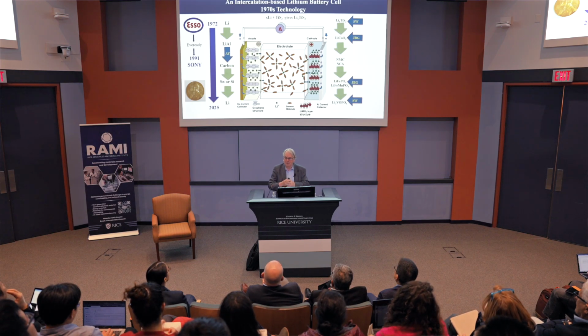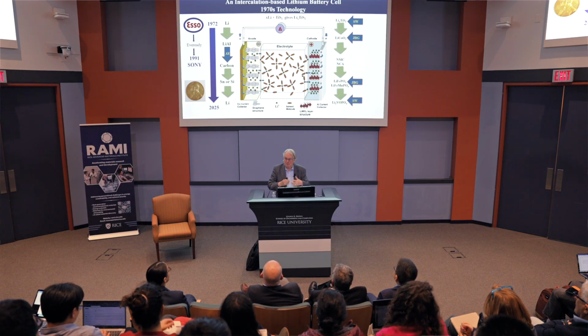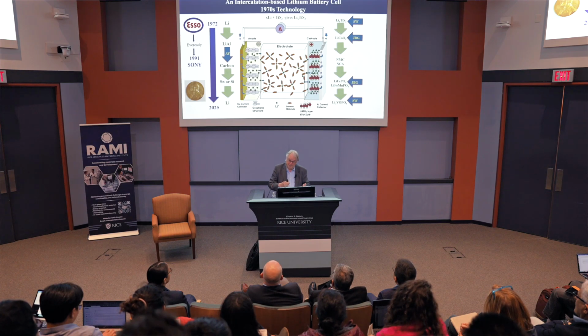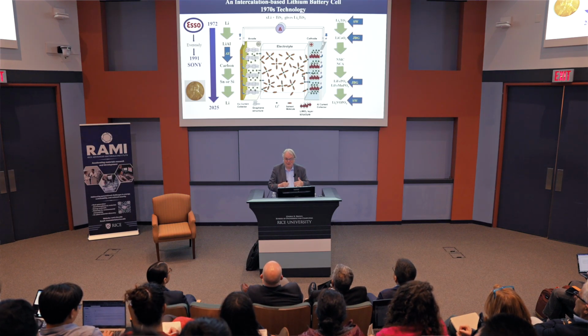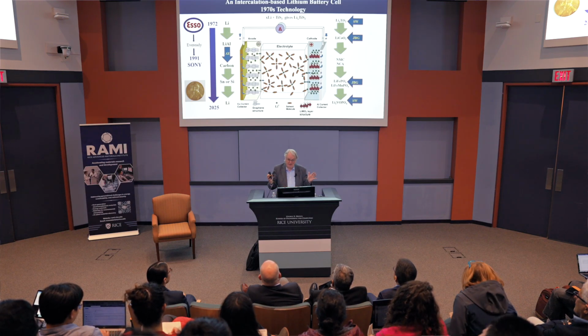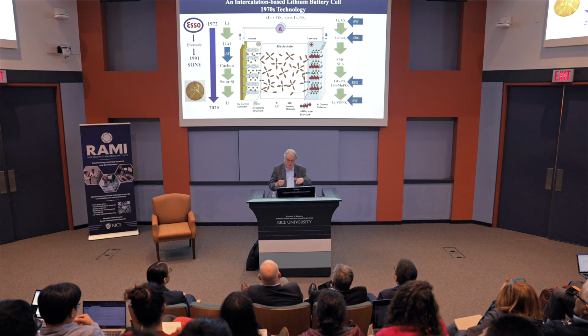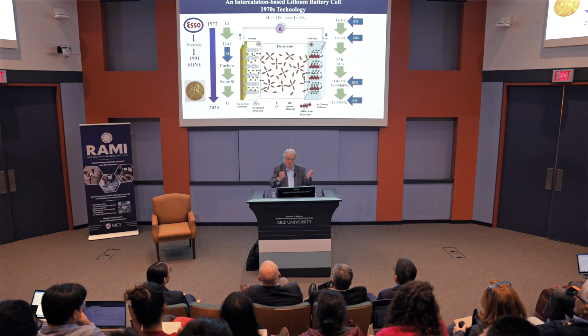So we started out with lithium metal. We realized there were issues. Any semiconductor person in the audience will know you don't want to get lithium anywhere near your semiconductor. It reacts with everything. What we switched to was using aluminum. Lithium reacts with aluminum at room temperature, a 1-to-1 alloy, and that works fairly well. But it doesn't last very long, because going from lithium to lithium aluminum, you're building a new structure, then destroying it, building it, and so on.